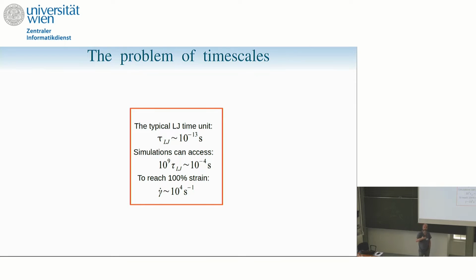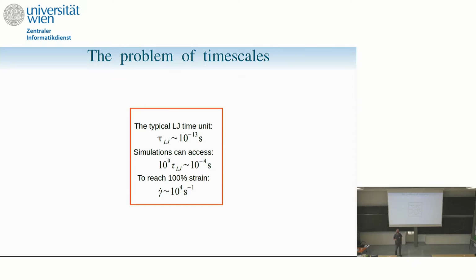So if you want to simulate shear, over the maximum accessible time, you want to shear your system by 100%, which even for steady flow maybe is not enough to reach steady flow, right? Most experimentalists would shear for hundreds of percent before reaching steady state. You have to shear at a rate which is 10^4 per second, which may not be where you want to see the important phenomena. And so, yeah, a priori there is an issue with timescales.